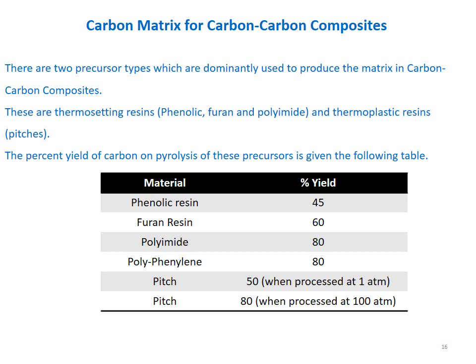So the percent yield of carbon on pyrolysis, that is, on heat treatment of these precursors, is given in the following table. Phenolic resins can produce 45% carbon. Furan can yield 60%. The yield of carbon from polyimide is almost 80%, and the yield of carbon from polyphenylene is about 80%, while the yield of carbon from a pitch depends upon the pressure applied during the heat treatment process. Pitch gives almost 50% yield of carbon when the process is carried out at 1 atmosphere, and its yield can be increased to 80% when the process is carried out at 100 atmospheres.